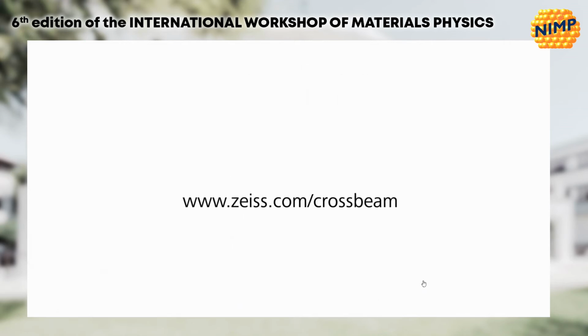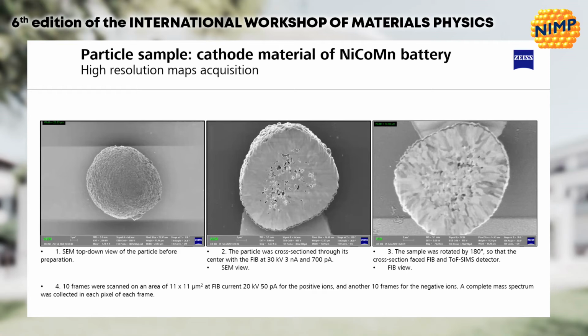The point is, in this case study, we use these techniques. In this case, there were the particles that I showed in the previous images, from the cathode of the batteries. We select a dedicated part of those cathodes. You remember this image was a square millimeter in high resolution, nanometer resolution. We select those particles. Then finally we make a transversal cut through these particles, polish the surface, and perform high resolution images, in this case with the electron microscope inside the dual beam system.